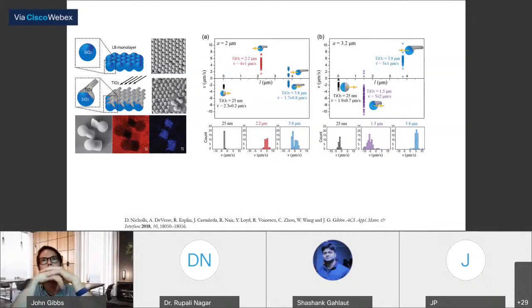One of the things that was interesting, and it's still not entirely clear why this occurs, but we have some ideas, is that you actually get this threshold value where the particle will start to move in one direction, and once the length of the tail gets a little bit longer, it'll actually switch directions. And we believe this has to do with the phoretic interaction between the fluid and the two different materials. And that interaction changes as a function of the geometry of the structures themselves.